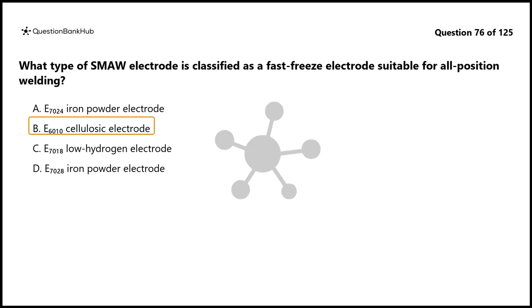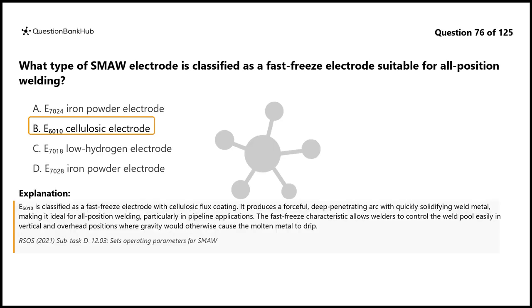The correct answer is B. E6010 cellulosic electrode. E6010 is classified as a fast freeze electrode with cellulosic flux coating. It produces a forceful, deep-penetrating arc with quickly solidifying weld metal, making it ideal for all-position welding, particularly in pipeline applications. The fast freeze characteristic allows welders to control the weld pool easily in vertical and overhead positions where gravity would otherwise cause the molten metal to drip.